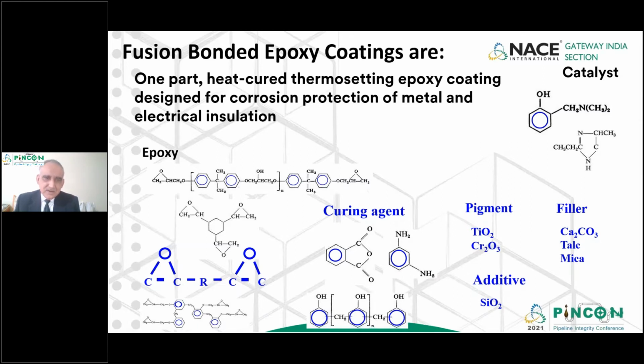Because during the application process, there is a requirement that the powder should form a gel, for a certain period of time, a few seconds, at a certain temperature. So there is a component called catalyst, which controls the gel time of the powder. And there is another chemical which is a curing agent, which helps to completely cross-link the epoxy resin. So there are two components, adjusted as per stoichiometry.